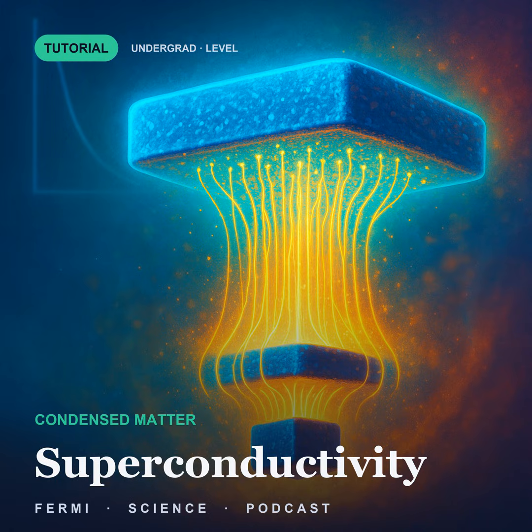With a voltage. 0.2 of a milli-electron volt is 0.2 of a millivolt, a number a bench voltmeter reads without complaint. So build a sandwich, a strip of ordinary metal, a layer of oxide a nanometer or 2 thick, and a strip of superconductor on top. Electrons can tunnel through the oxide, feebly. Apply a voltage and measure the current. And the current tells me about the states on the far side, because an electron can only tunnel into somewhere it is allowed to be.